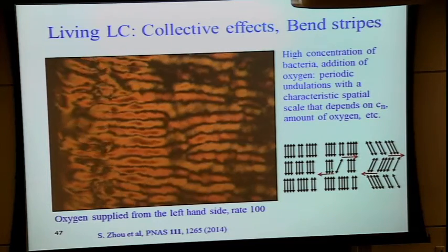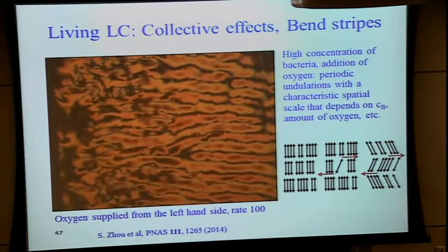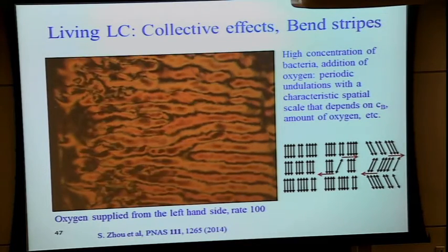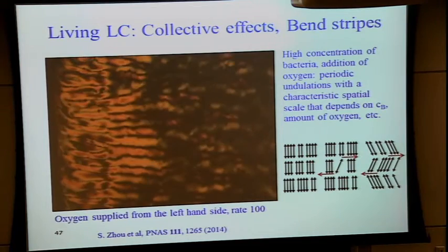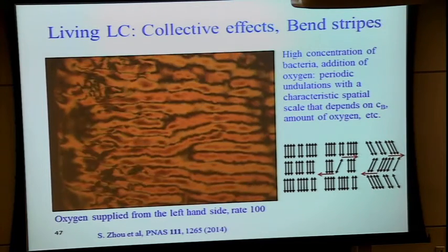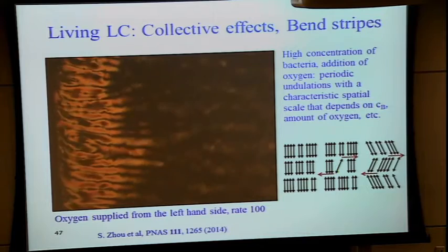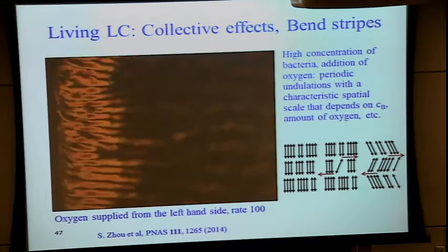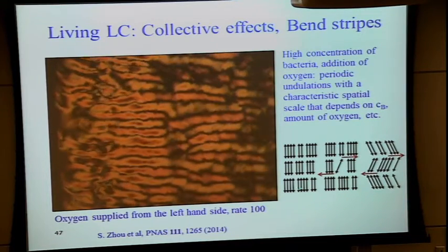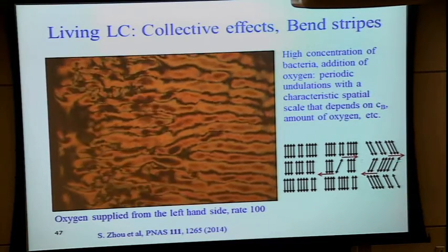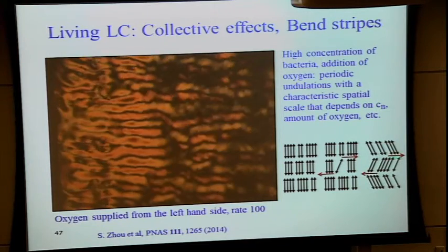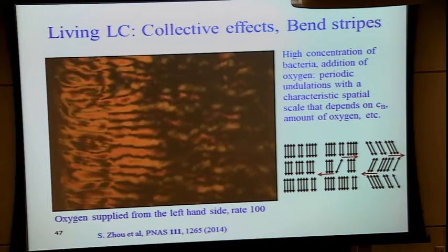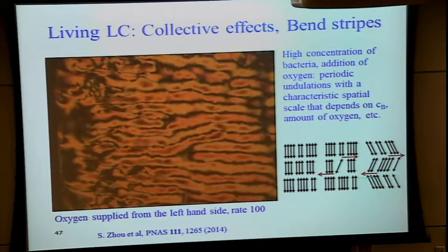If you have an active particle of the pusher type embedded in the nematic environment, what happens is that if by any fluctuation this particle slightly tilts with respect to the rest of the medium, with respect to the director, then there is a projection of these jets of flow, in our case, onto the horizontal direction, and the nematic becomes unstable with respect to bulging towards these red arrows to the right or to the left.